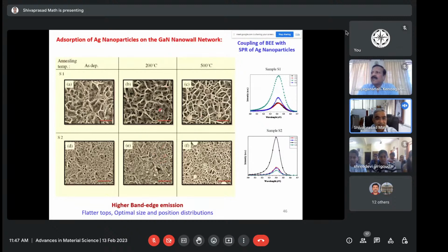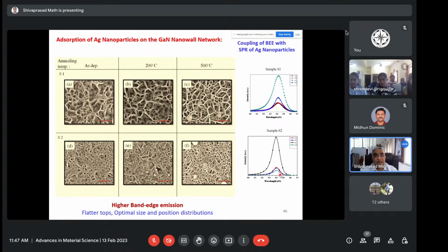You can see these tiny circular spherical things we put on these materials and looked at. And lo and behold, there was a huge increase in signal. It had already increased from the commercial, as I told you earlier, and now it increased almost another 100 times. So we were able to increase the signal from the commercial film to about 500 times by just making different nanostructures. That I think was very important.